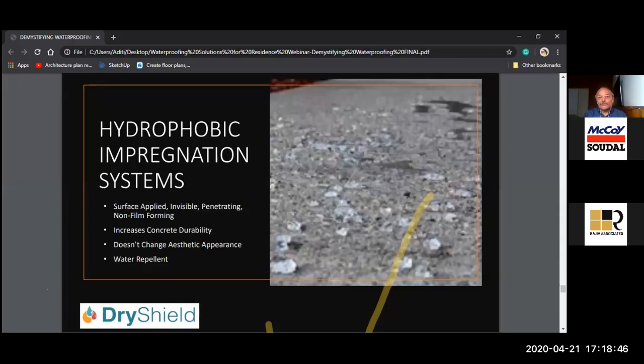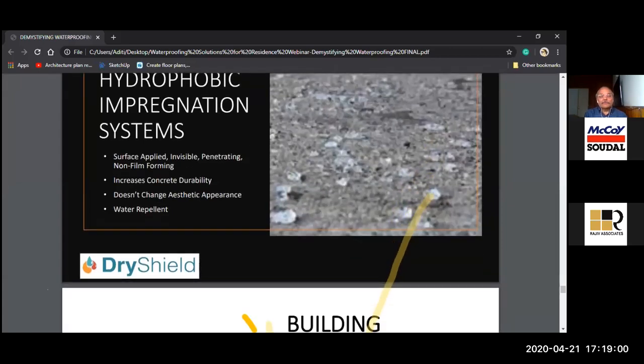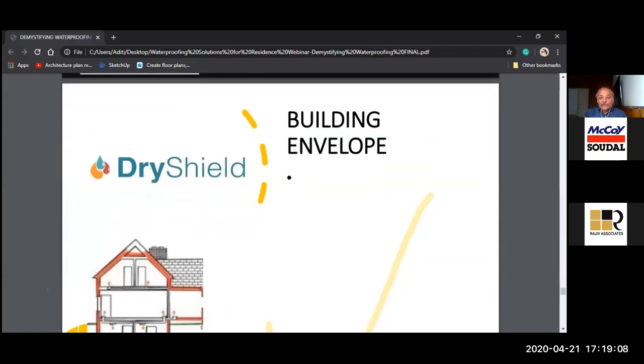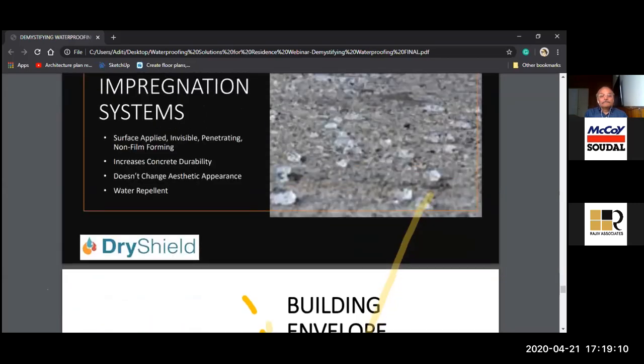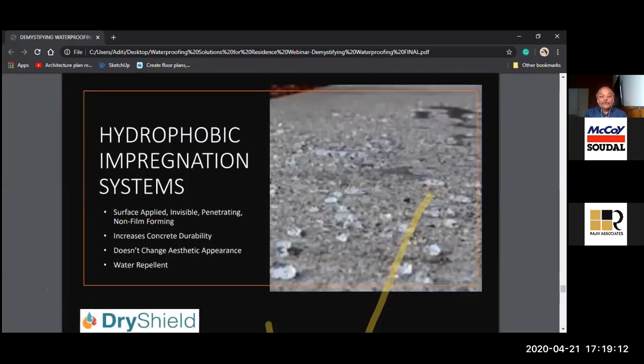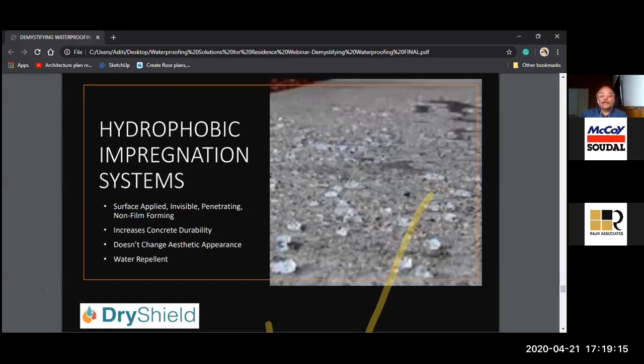There are some companies who recommend spraying it with a handheld spray pump, kind of an agriculture pump. And these are to be used pure, no water has to be mixed in this. So most of the coatings, like PU also, you cannot mix any water in it. Hydrophobic impregnation systems can be used anywhere on the walls, stone walls.